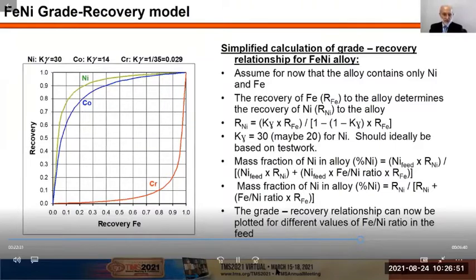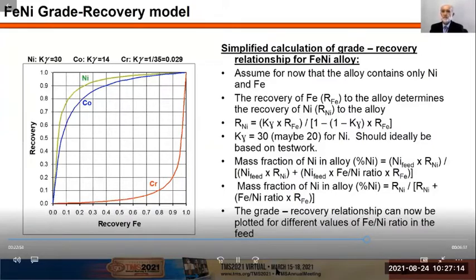The graph shown on the left is really the results of that thermodynamic approach, where we have plotted the recovery of nickel, cobalt, and chromium as a function of the recovery of iron. The values of K gamma chosen are based on experimental work, but could equally have been derived simply from a literature study. So in our simplified model, we can assume for now just the nickel and iron components, and we've used this curve then to show the recovery of nickel using our equation. The value of K gamma that we have used for nickel is about 30. This could perhaps be as low as 20, and it should ideally be based on test work.